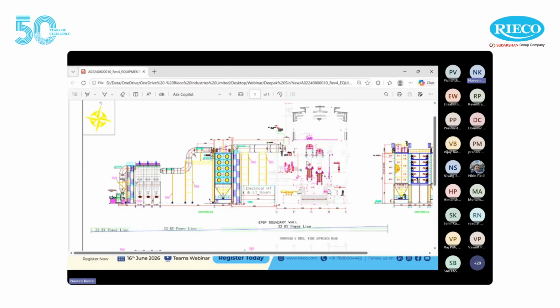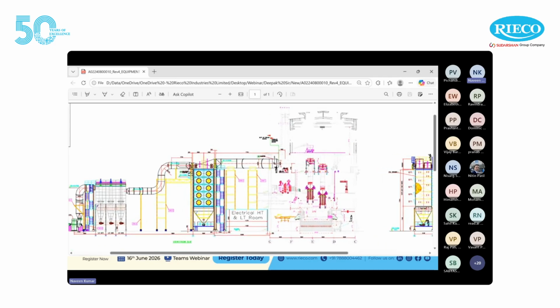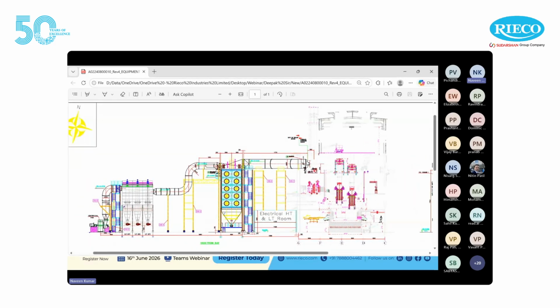which are typically specified by furnace capacity in MVA: 9 MVA, 30 MVA, 16.5 MVA. These are the furnace capacities that have been defined as limiting capacities. This is a typical layout where, as I showed, there is the submerged arc furnace and one tapping duct from the submerged arc furnace top, which first flows to the air-to-air heat exchanger, where we also look at the axial flow fans with the inlet temperature, and we can optimize the power consumption by varying the number of axial flow fans running based on the inlet temperature.